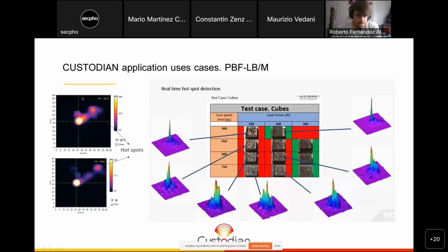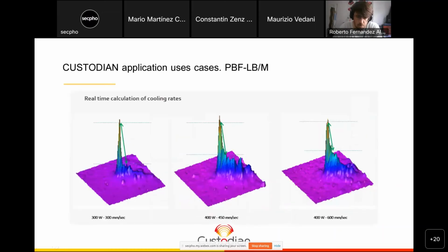These are some examples of images we obtain. We can see where the main spot is located, and we always see some kind of melt pool or tail from the process. We can also visualize a hotspot or projections from the process using the camera. As we can see, we have enough spatial resolution even to try to measure the cooling rates from the process.